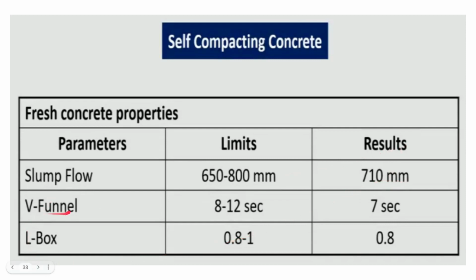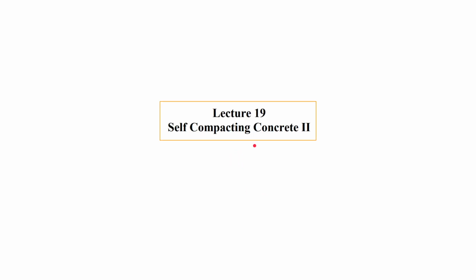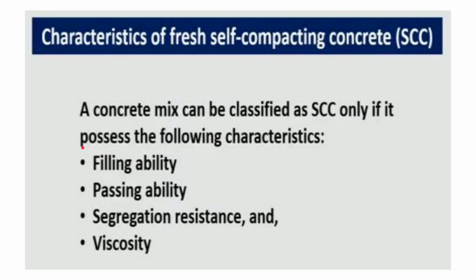Okay, the V funnel, which is used for viscosity, we will go through. So the V funnel is basically used for viscosity checking. It should come between 8 to 12 seconds, and 7 seconds is found. And the L box, which is a passing or filling test, should come between 0.8 to 1, and results have also found similar values. Okay, so let us now go to the next lecture on self compacting concrete.